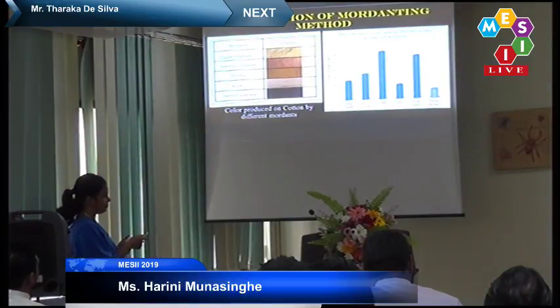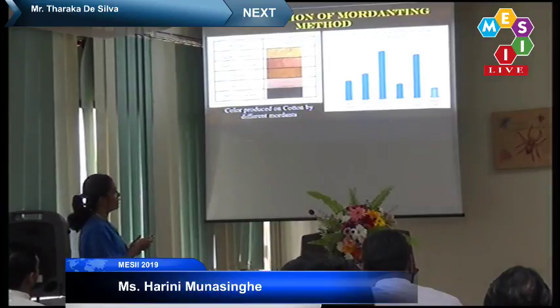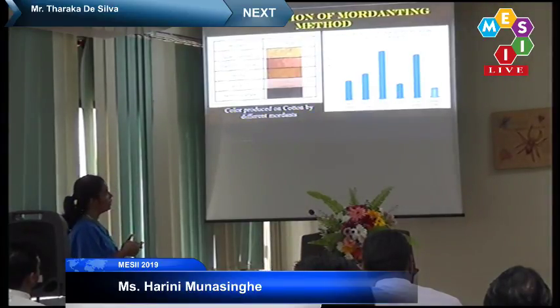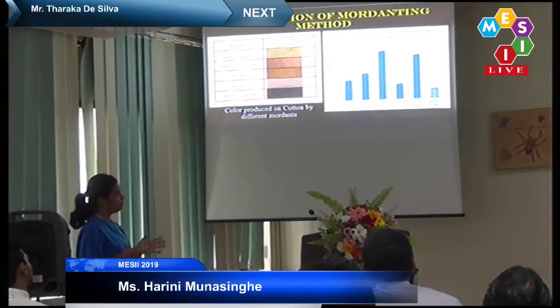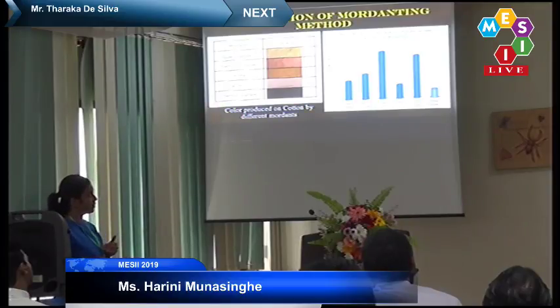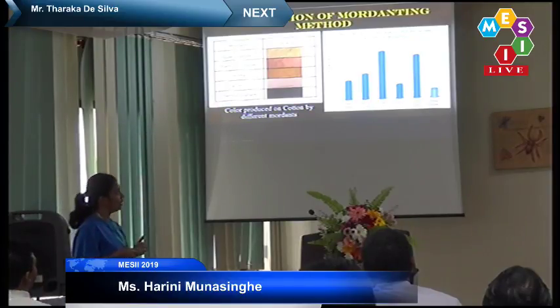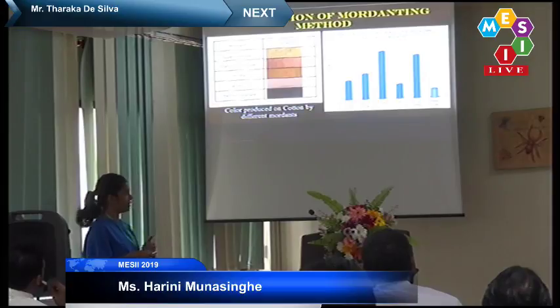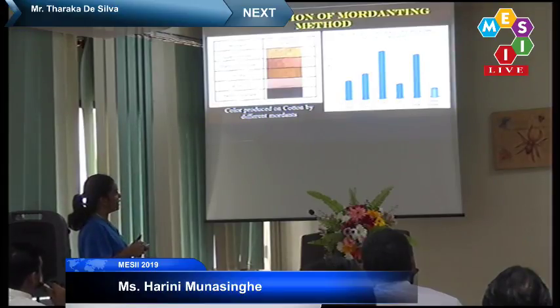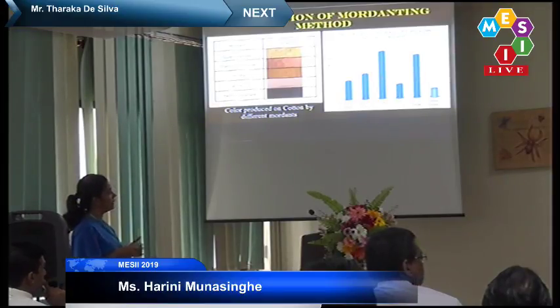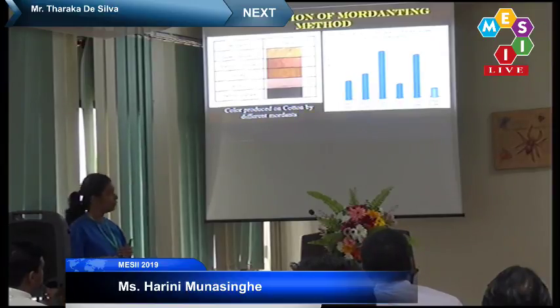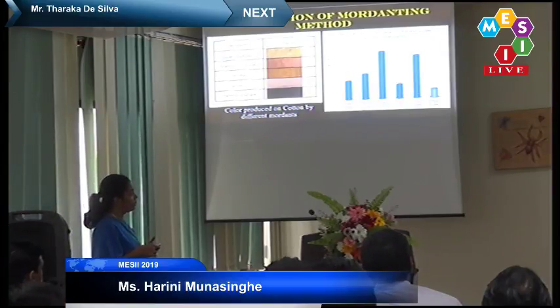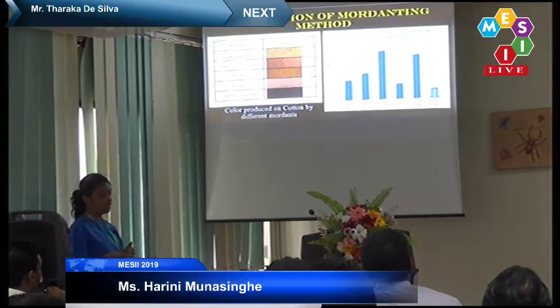And this is the color strength value which can be obtained from each dye and each mordant, and from this graph we can say which mordant gives the highest color strength value for the pre-mordanting method using monkey tail flower extracted dye. And here you can see that the chrome and the ferrous sulfate mordants give high color strength values, and also alum, meaning aluminium sulfate, gives less color strength values.